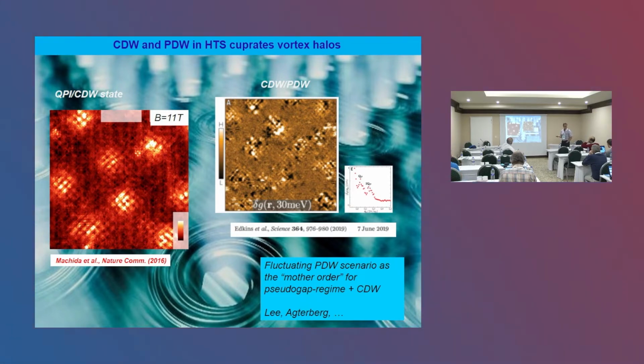so the vortices are generated in the sample, the location of the vortex core is a very interesting site, because it's a place where superconductivity is destroyed, the order parameter vanishes, and then the center of the vortices reveals over the years a lot of modulation, like in this measurement in 2016, a mixed charge density wave or quasiparticle interference states seen in the core of the vortices, and more recently oscillations which were associated with the charge density wave and pair density wave, which in some scenario might be the mother order to generate the pseudogap or the charge density wave, which are seen in X-ray measurements.